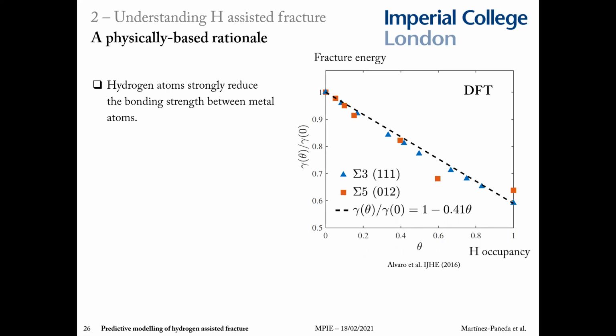The first one is that atomistic calculations show that the bonding strength between metal atoms is reduced with hydrogen occupancy. You can see here a DFT result of surface or fracture energy versus hydrogen occupancy. This is for nickel. And you can see that if we have enough hydrogen, if we're on this side of the graph, then the cleavage strength or the grain boundary strength will be much weaker. And there has been a bit of a discussion in the atomistic community in regards to quantifying how strong this effect is. And a big part of the controversy relates to figuring out how much hydrogen you actually have. So where are you in this x-axis, this hydrogen occupancy?